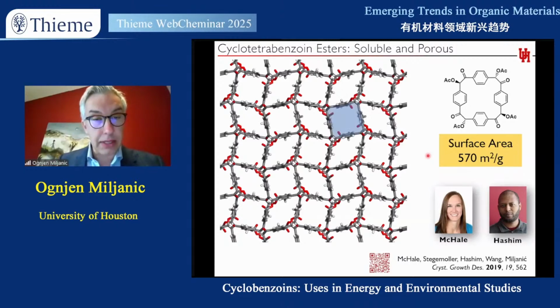And so what we see in this crystal structure is the square-shaped pore, which comes from the macrocycle itself, but the square-shaped pore is surrounded by the cycle in the solid state. And we have noticed that despite the fact that we can produce these crystals from a variety of different solvent conditions, the packing is always the same. And so this is a monomorphous material. And the hydrogen bonding is now gone, but this molecule simply seems to have a very awkward shape, which permits no closer packing than the one we observed. And this is the work of my 2 former graduate students, now in chemical industry, Corey McHale and Mohammed Hashim.